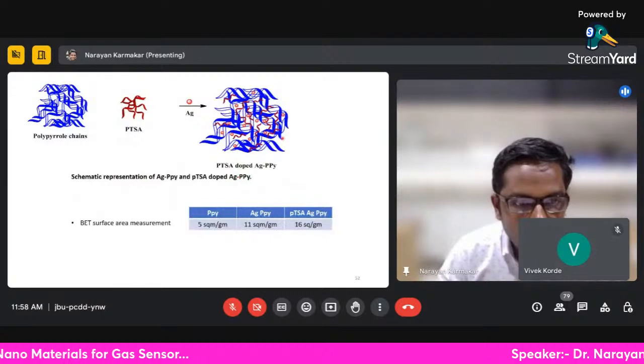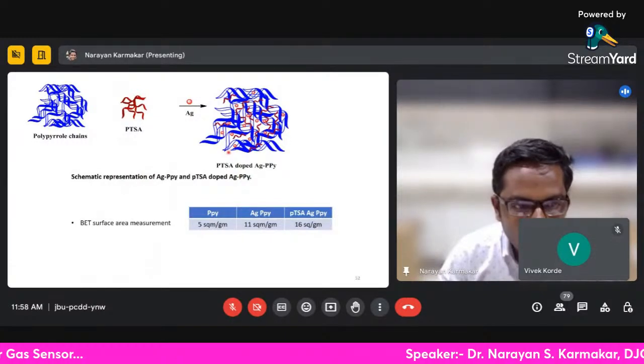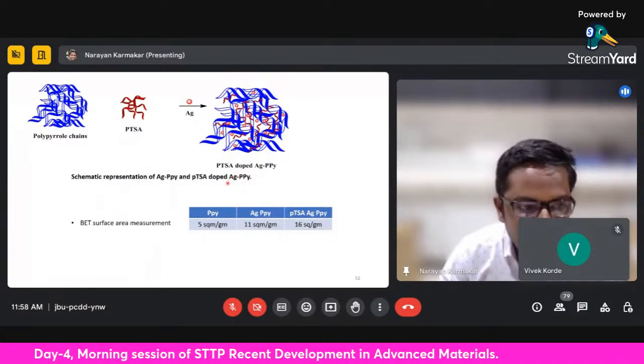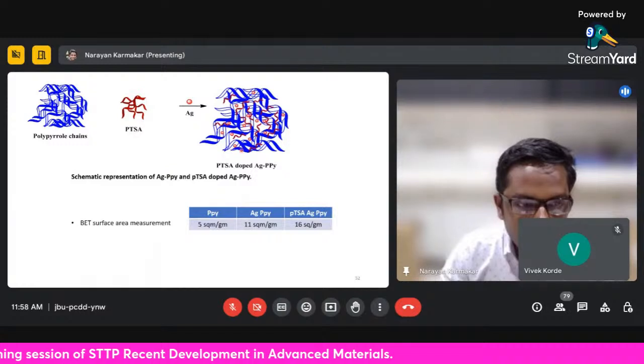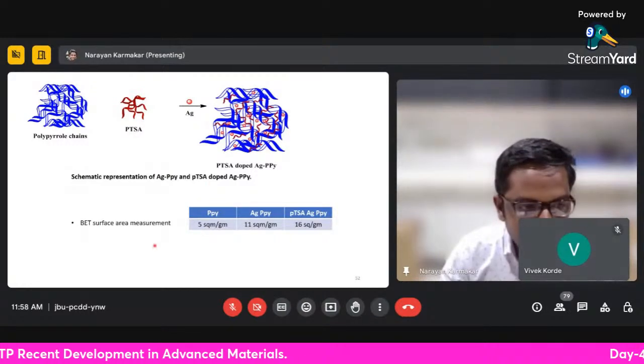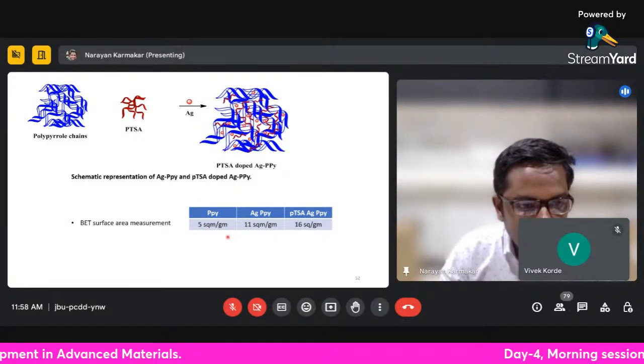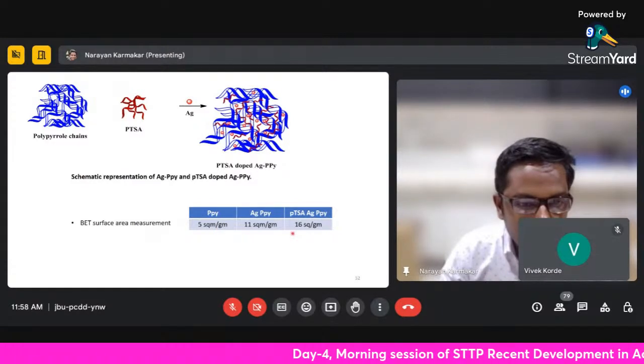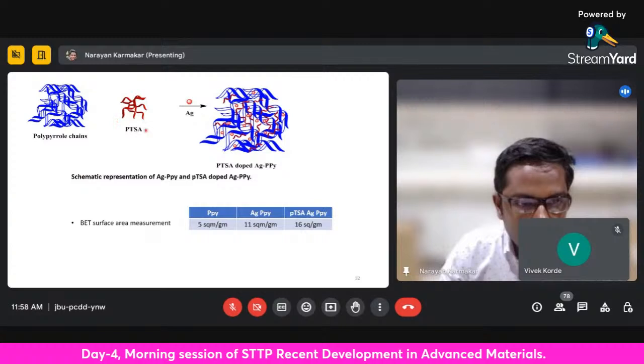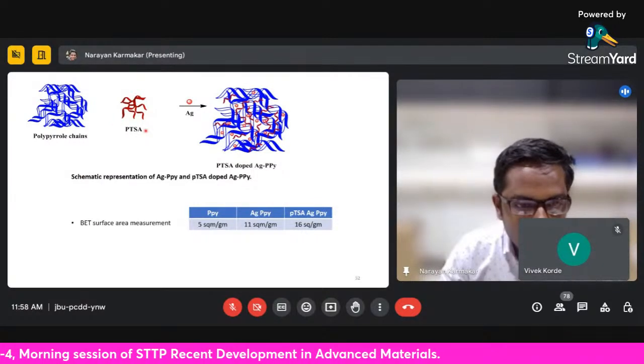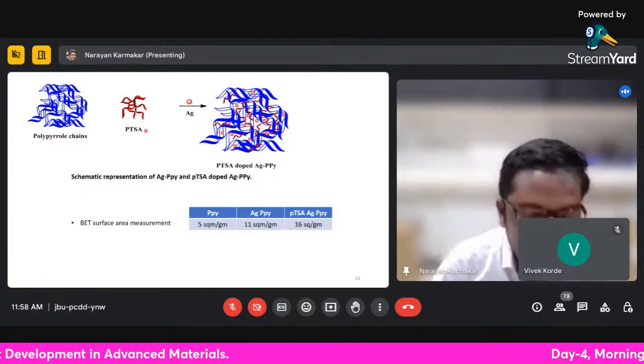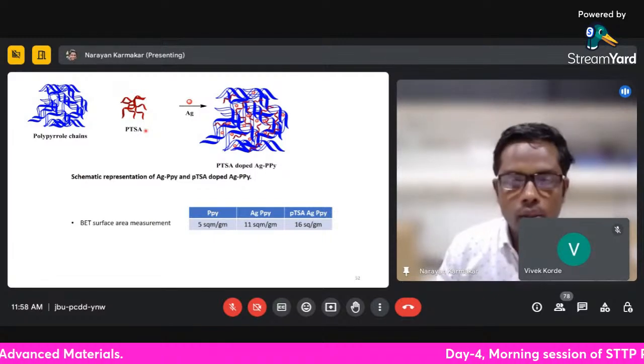Because of this doping, it becomes a porous structure, and this was confirmed using BET measurement. Using BET measurement, we saw that for PPY it was about 5, and for the PTSA doped sample it was about 16. So after doping with PTSA, the structure becomes more porous, and because of that, the absorption and desorption of these gases increases rapidly.